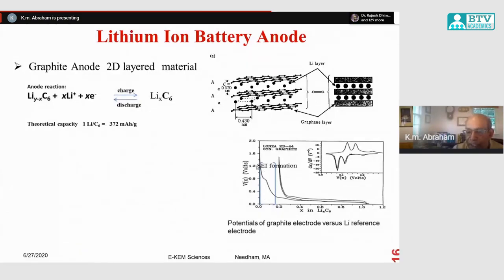This is simply showing the electrochemical behavior of your graphite electrode. As you can see here, this is the first charge of your graphite electrode. When you charge it first, you can see that there is this first part where there is some capacity. This particular cell has capacity in this region because you have a reduction at a higher potential than 0 volt. Otherwise, it should just come down.